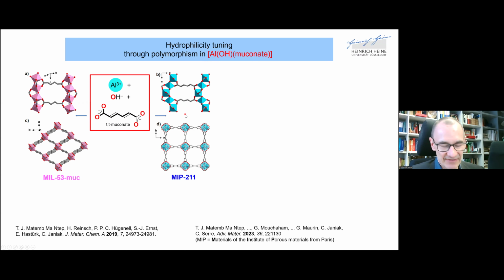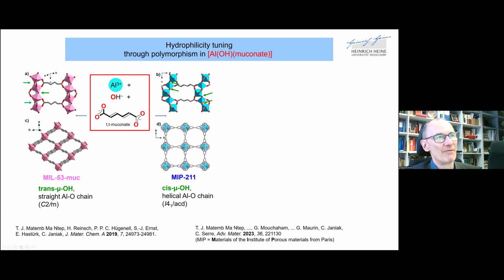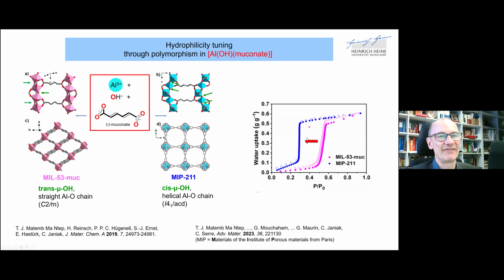What else was different besides the structure? That was the orientation of the hydroxyl groups bridging the aluminum atoms. Here in this MIL-53 muconate polymorph, it was trans-oriented. In the MIP-211 polymorph, it was cis-oriented. It seems like a small change, but that change has a drastic effect on the region where the water uptake occurs. The left polymorph, MIL-53, is still quite hydrophobic, apparently, because its water uptake occurs at roughly 0.5 relative pressure, while the MIP-211 polymorph, with the square channels and the cis orientation, has much higher hydrophilicity.